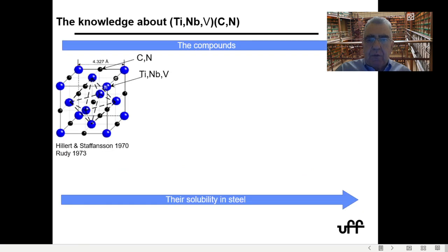Now, continuing on the same line, then in the 70s, Mats Hillert and Staffansson developed this model of the compound energy formalism, and it's interesting enough, Rudy did the same some 3 years later, and the idea was that if you have the miscibility of two compounds like titanium nitride or titanium carbide, niobium carbide, and so on, you can assume that there's mixing in different sublattices. This became a really important movement in the CALPHAD community. It was based on the mixed salt ideas.